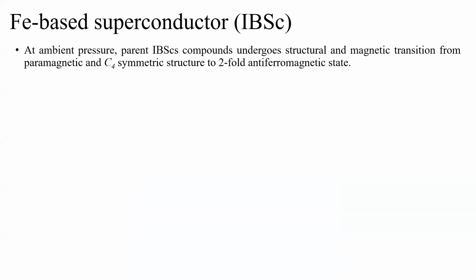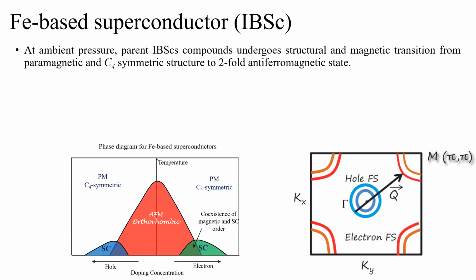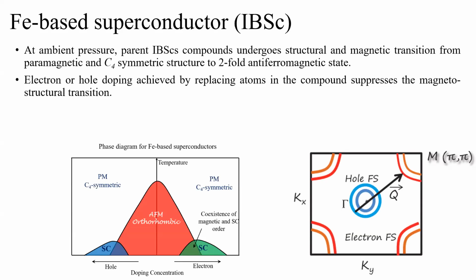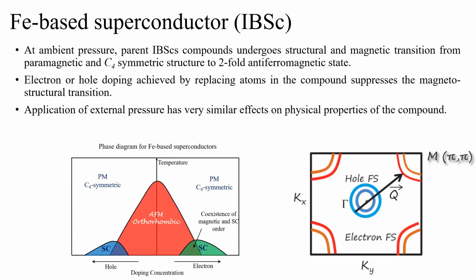Now, these compounds also have other properties. Most of these compounds are C4 symmetric and paramagnetic at room temperature, and when you cool down below a certain temperature, which depends on the compound you are studying, it goes to a different structure with different magnetic ordering. This lower temperature state is a two-fold antiferromagnetic state. And if you dope electrons or holes at different sites of the compound, you can tune the properties of the material. The magnetic transition that you expect in the parent compound is suppressed with the electron or hole doping, and then you observe a superconducting phase within a critical doping range, which is also known as a superconducting dome. Usually people also find this in copper-based superconductors.